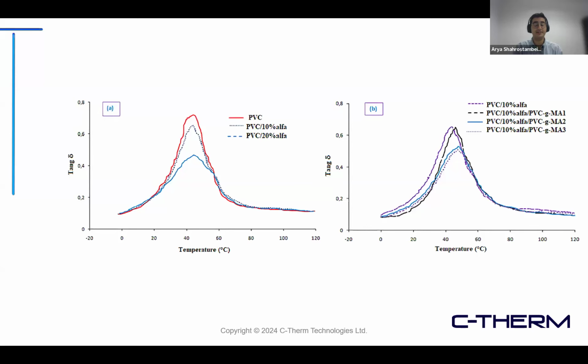These are the same tests, but the data is plotted as tan delta over temperature. So instead of using elastic modulus, we have used the loss factor, or the ability of the material to dissipate energy through its matrix. You can see that PVC has a higher peak over the temperature on the left-hand side, and as we are adding more fiber, we have a shorter peak in terms of height. It means that the higher the peak, the softer the material becomes, because don't forget that in the numerator you have your loss modulus, and in the denominator you have your storage modulus. So the more the loss modulus, the higher the tan delta peak, and the softer your material becomes. As expected, they observed that behavior.